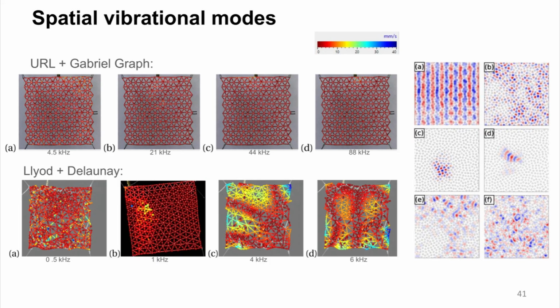As we can see, at 1 kilohertz there is concentration of vibration in the interior region of the metamaterial, whereas for some other frequencies like 4 and 6 kilohertz we do see some plane waves, and for lower frequencies there is a dispersed vibrational mode. And this is similar to what has been predicted in computational studies. This study was done on a hyperuniform distribution of lead in an epoxy matrix, on the acoustic properties of that medium.